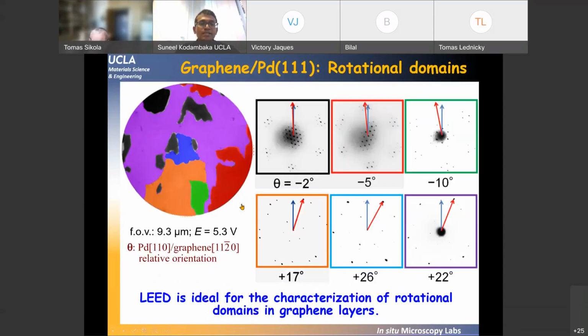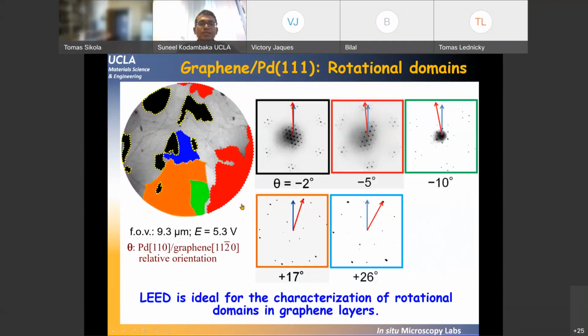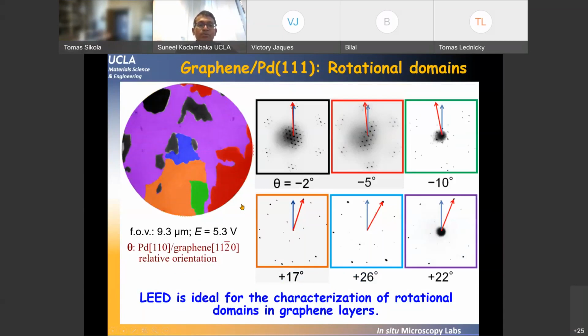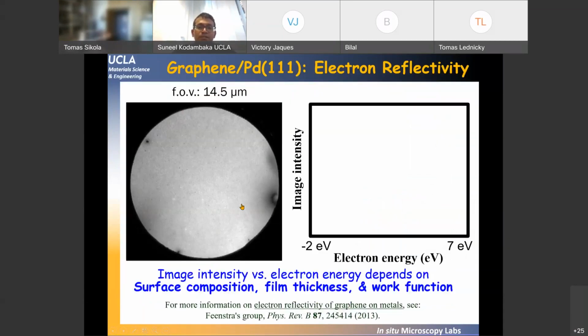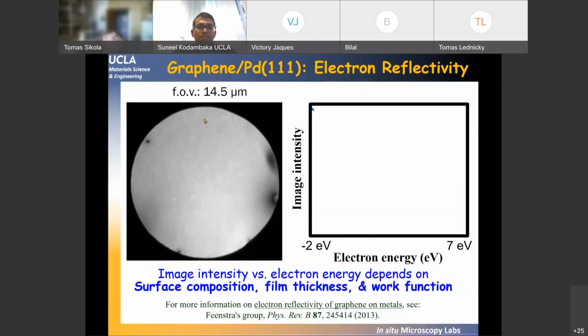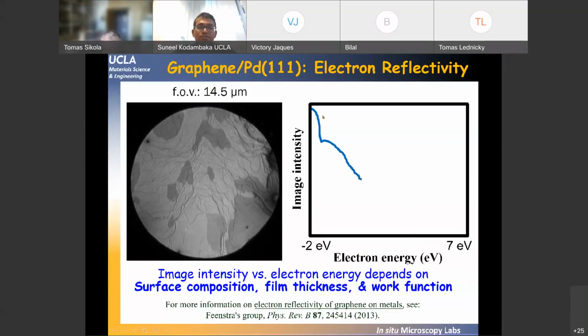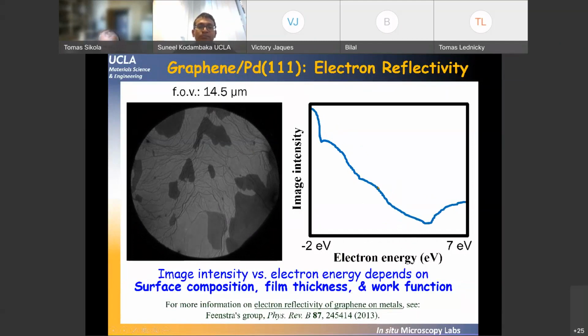Now, the other thing you may have seen here is that these domains look different in contrast. And that is because of the amount of electrons that are reflected from the surface, and that depends on the surface structure. And so we can quantify this behavior by using what is known as an electron reflectivity measurement. What is done here is that you collect the intensity from a given field of view, and you plot it as a function of the incident electron energy. So you sweep the electron energy while imaging the same field of view, and watch what you see. So this is the total intensity of this image as a function of electron energy. And as you change it, you see the intensity changes. Such a curve is called a reflectivity curve. And this change in intensity is a measure of the electronic structure of a given area.